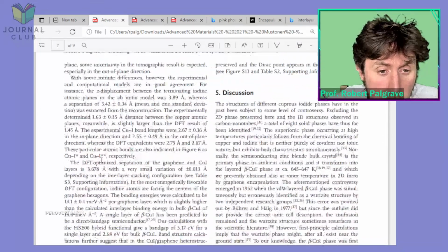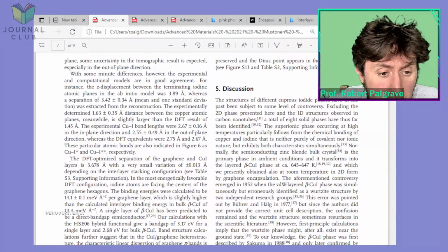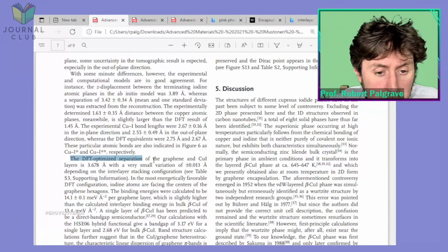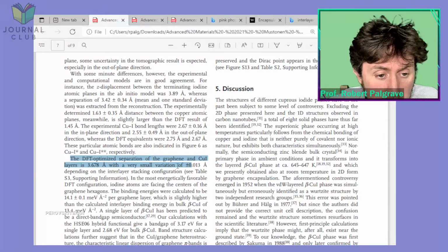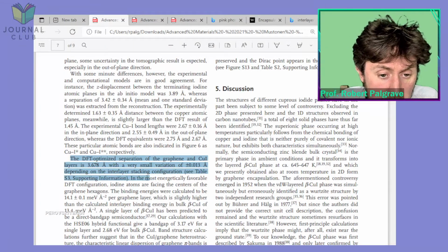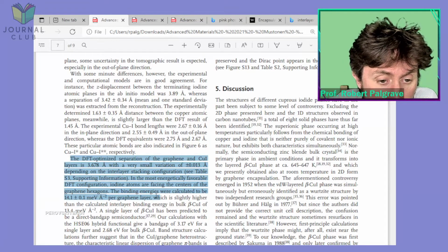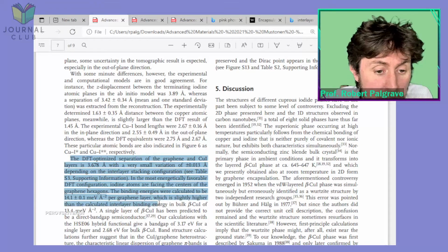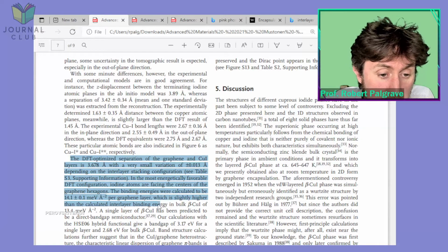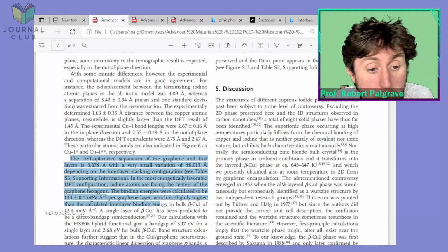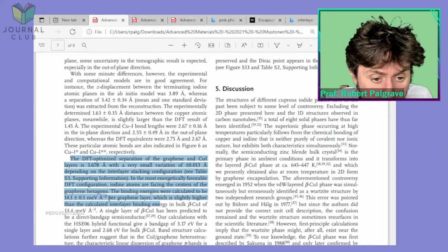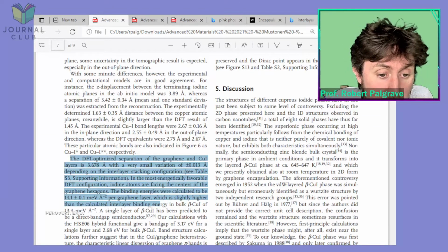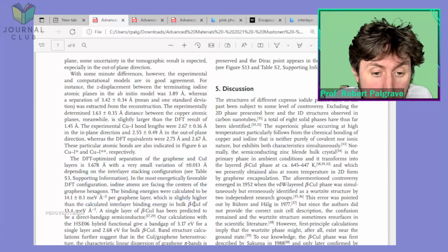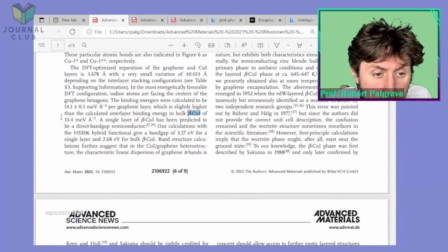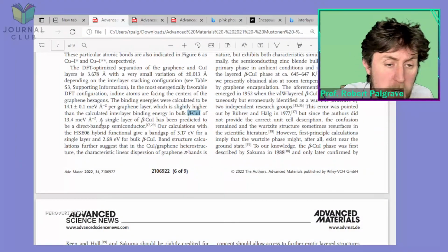Okay, let's have a quick look at this. The DFT optimized separation of the graphene and cuprous iodide layers is 3.678 angstroms with a very small variation depending on the interlayer stacking configuration. In the most energetically favorable DFT configuration, iodine atoms are facing the centers of the graphene hexagons. The binding energies are calculated to be 14.1 milli-electron volts per angstrom squared per graphene layer, which is slightly higher than the calculated interlayer binding energy of bulk beta cuprous iodide of 13.4 milli-electron volts per angstrom squared.